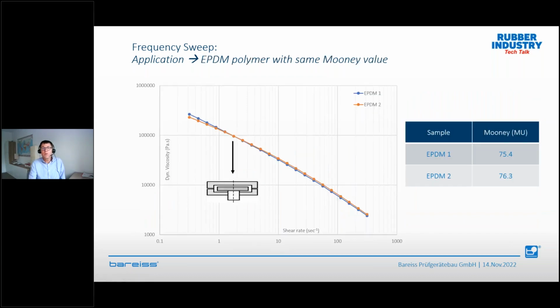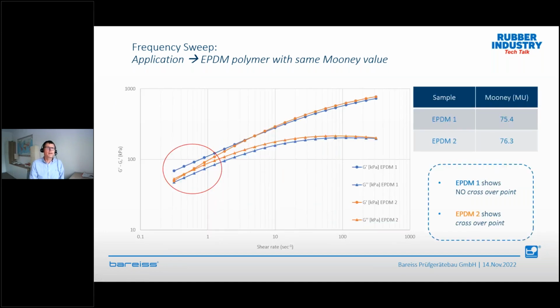So again, we have these two examples, EPDM 1 and EPDM 2, and they both have more or less the same Mooney viscosity. If we plot the dynamic viscosity and look at the range of the shear rate of Mooney, yes, they are definitely the same. We see a little bit of difference here and here, but it's a log scale. So we will see more if we plot G prime and G double prime again.